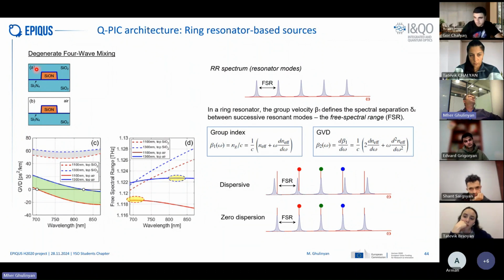We noticed that if we make the system with covered oxide on top of your ring resonator, so this is the waveguide of the ring resonator, your dispersion is not good, and you would like to have a zero dispersion at some point. By removing the top layer on top of the ring, we can tune it perfectly, and then you can see that in these devices, which are the dark full line curves here, you can have the flat situations for the free spectral range. So the free spectral range here is very constant and is not changing.